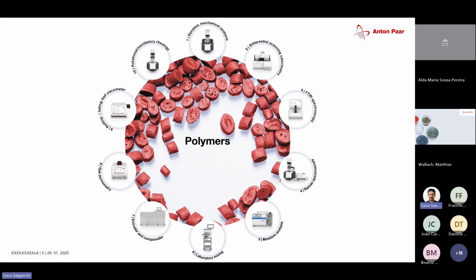Is anyone using gas pycnometry currently? Are you familiar with gas pycnometry? This is used to measure the density of polymers. Typically, you have your polymer, then you melt it and hot press it, then you have a specimen which you put into water at a specific temperature, and then you wash it out of the water displacement. That gives you the bulk density. The problem is this takes a lot of time, typically 40 minutes to an hour, depending on how good the operator is. Gas pycnometry is an alternative way to do this.